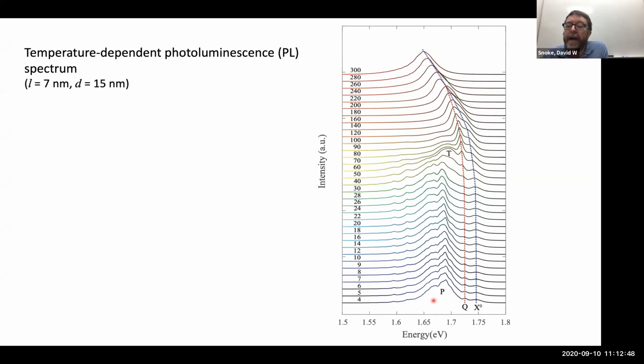Now, this is a doped system, remember, and it's p-doped. We have a set of impurity lines, and the range of these impurity lines is also very well established in these things. And so what we see is those saturate both as you increase temperature and as you increase the density. So there's only a finite number of impurities. As you raise the temperature, all of the carriers pop off of the impurities. And if you raise the density, there's only so many impurities around, and so things are going to saturate that way as well.